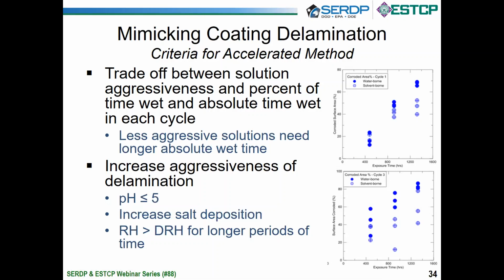So both of these fully dry, but cycle 3 has a much longer time in the cycles. And I just want to point out that you can see the amount of surface delamination, which is basically coating peeling off the surface, is greater the longer the time I have in any given wet cycle, even again for the same total time of wetness. But because of the aggressiveness of attack, which is directly related to coating delamination, in this more aggressive environment, you can see that this may be one of the tools we have. At 500 hours, we can distinguish coating performance. Whereas for those of you who run salt fog, you can run it for 3,000 hours and not see any difference.